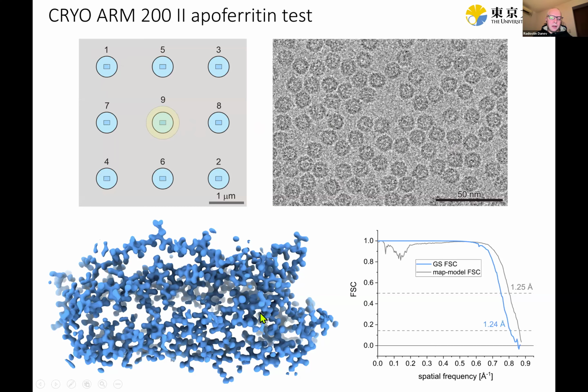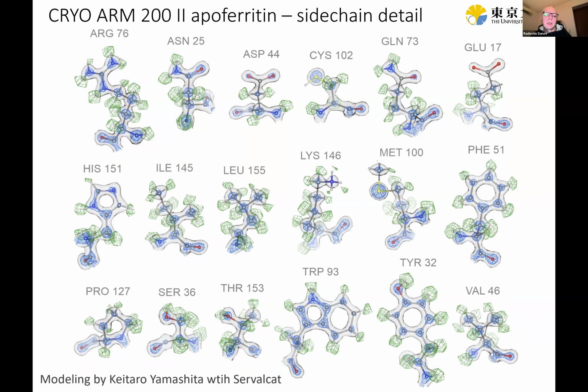Then after reconstruction, this is what the map looks like, and the data reached 1.24 angstrom, which we call, according to the current consensus, atomic resolution. Then Yamashita-san from the University of Tokyo, who is actually the creator of the ServalCat software, was very kind to help with the modeling of this map. So here you see representative side chain densities and also the model. The gray surface shows the map at the lower threshold, the typical one which is used to show the map. Then at a higher threshold, we have the blue surface, where you can see individual blobs for the non-hydrogen atoms in most of the side chains.